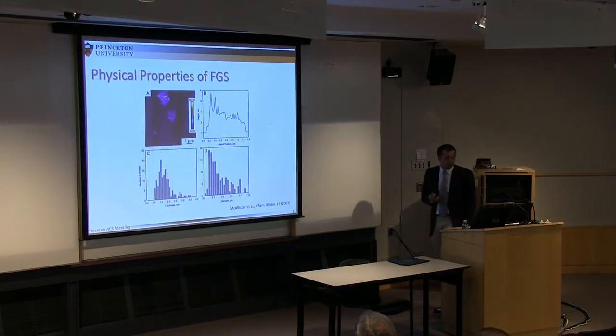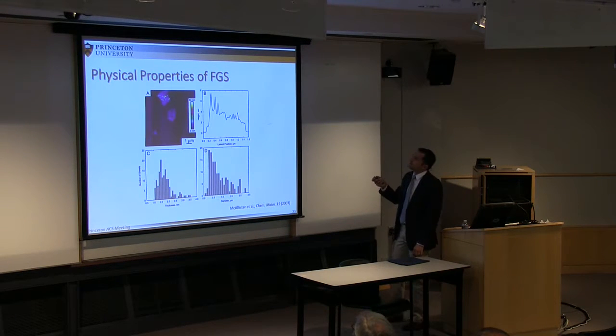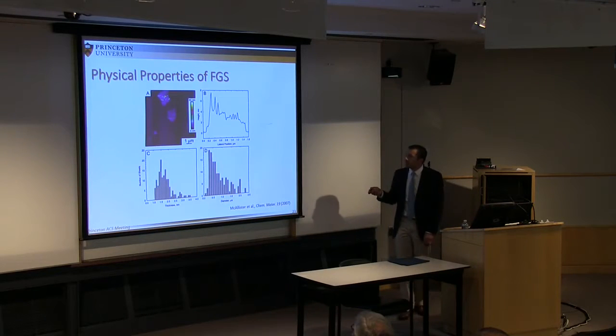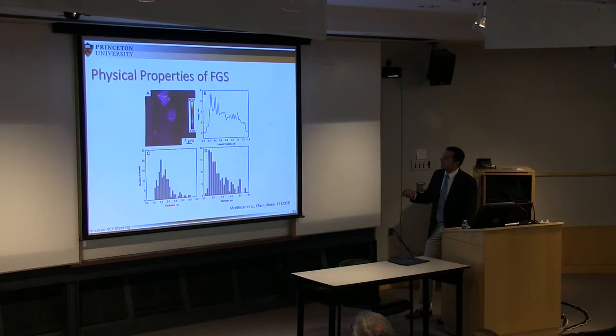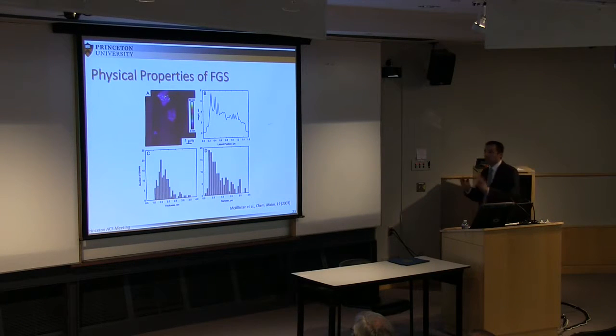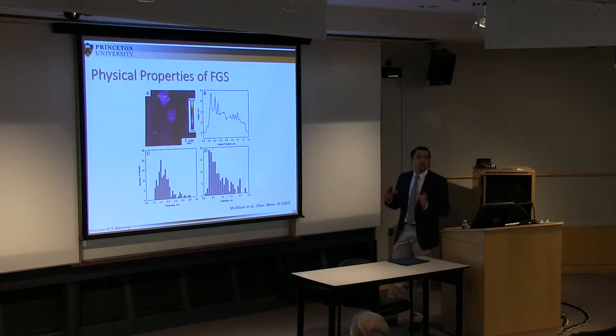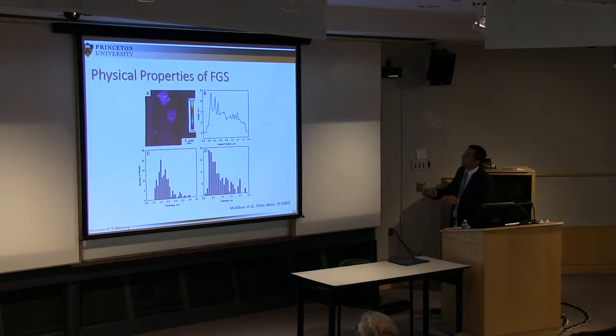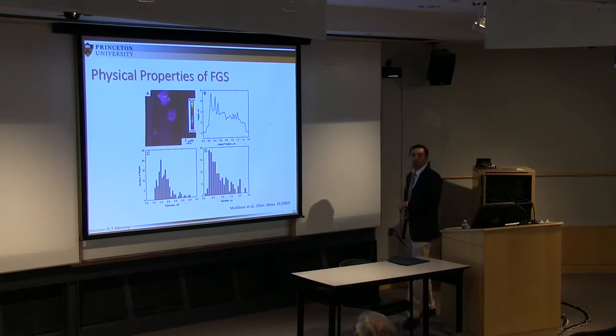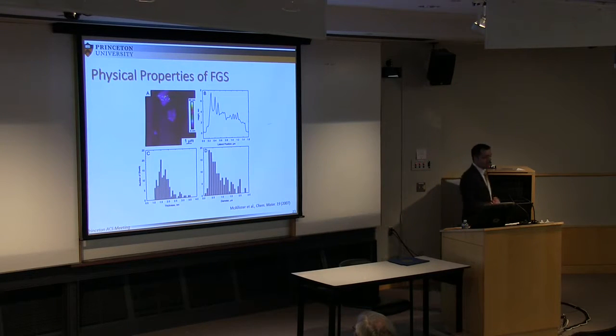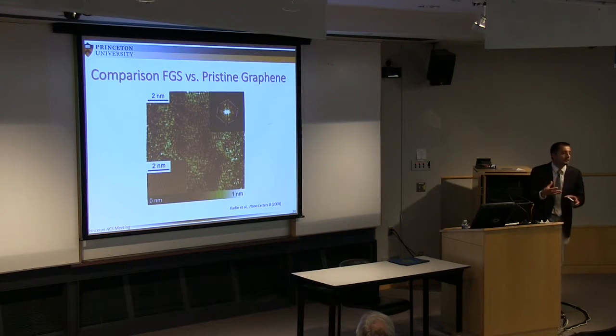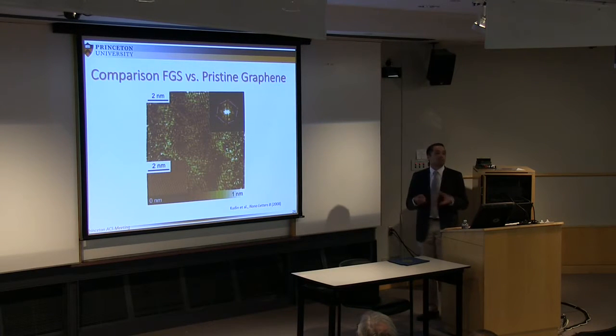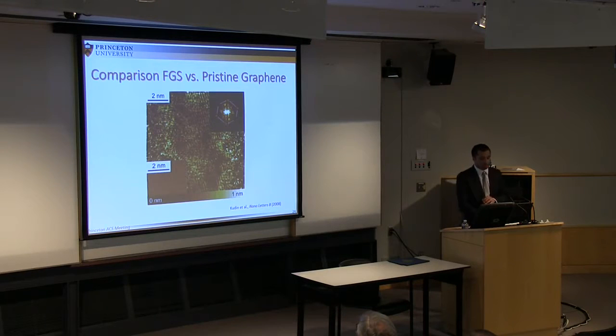If you look now at the physical properties of this material under the AFM, so this is the material that has been heated, you see that the population that has a thickness of about 1.8 nanometer is the majority. So that's the value we are taking as a reference. And if you look at the dimension now, the diameter of this graphene sheet, you see that they mostly range on the order of a few hundred nanometers. So you can also have graphene sheets that can be as large as a few tens of microns. But it's never going to be hundreds of microns due to several reasons. One of them is the initial graphite plate size that we are starting with, and then you are limited anyway in your process because of the periodic cracking of the graphite plate.